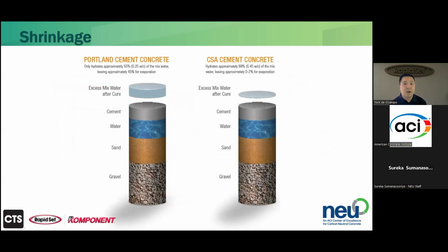So the question is, how is the shrinkage lower? The answer lies in the amount of water required to hydrate CSA cement. I've often heard it said that the water demand in CSA cement is higher, and while that's technically true, it doesn't necessarily mean the water cement ratio is anything crazy or out of the ordinary for the concrete mix design. The real reason the difference is so stark is that in Portland cement concrete, most of the water, or a significant portion, is basically water of convenience.